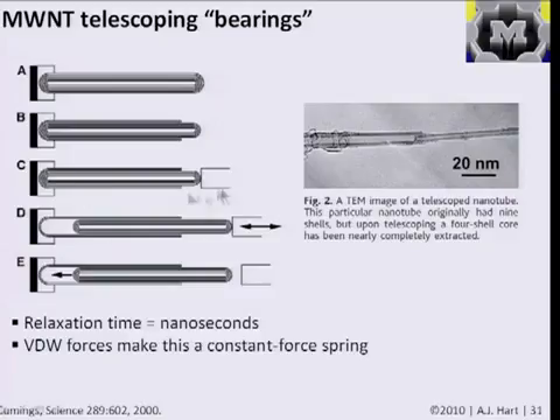And if you look at the paper, you would see that they measured the force necessary to pull the tube out. And effectively, because of the radial balance of the interaction forces, if you looked at this end on, the force necessary to pull this out is very little and is just related to the effective sort of sliding resistance of the inside of the tube against the outside of the tube. And this is something that also, because of the energy, because of the system wanting to minimize its energy, if you let it go, it snaps back really fast. And they say it snaps back in a matter of nanoseconds.